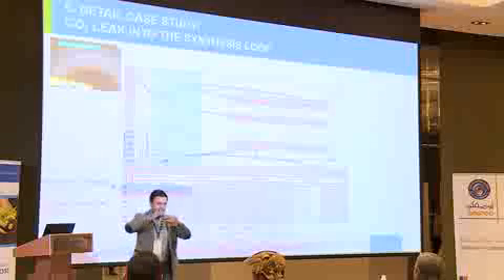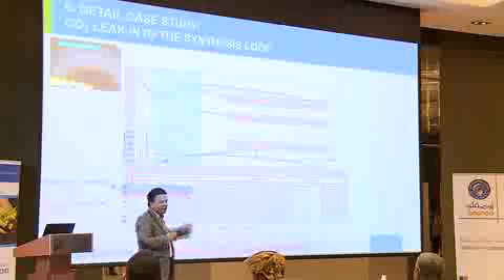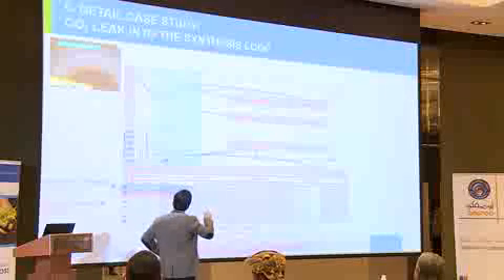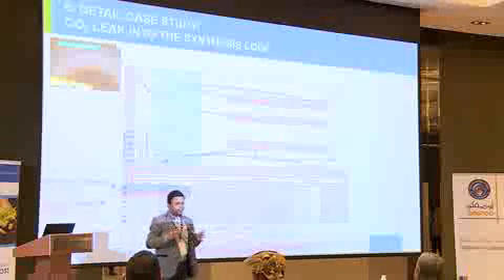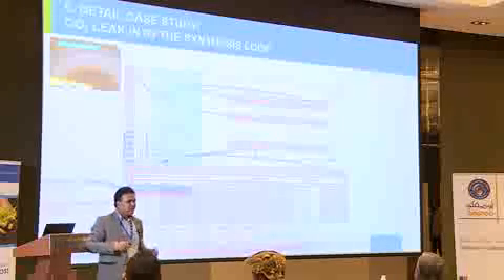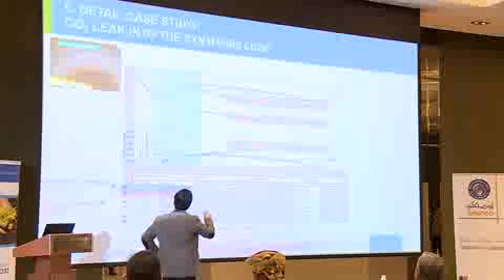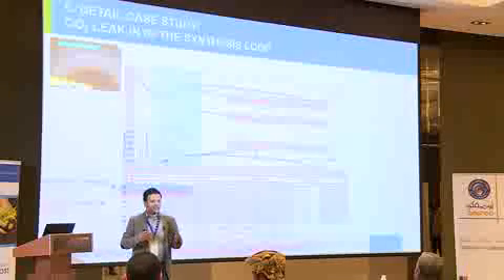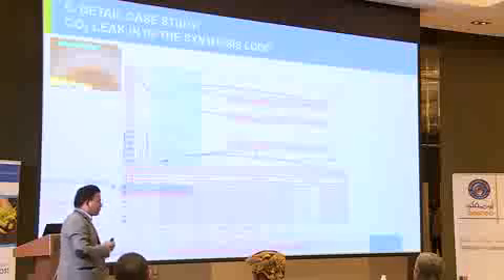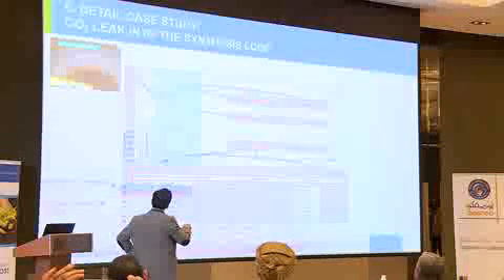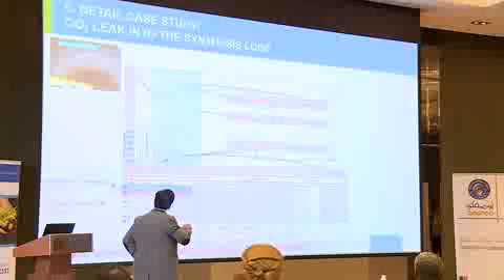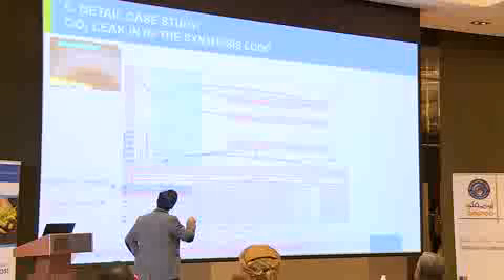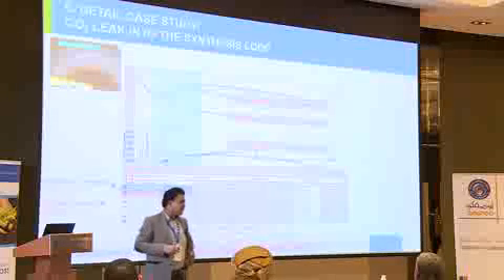This theory was further clarified when they looked at the top temperature of the stripper, the off-gas temperature of the stripper going to HPCC and ultimately to the reactor. They saw during that time there was a dip in the temperature. This is a fully traced line. So when there is no flow, it should have a fixed temperature. But during that period, the temperature was decreasing. So there must be something flowing through it. So the theory became stronger: the pressure of synthesis was lower compared to the compressor, and there was a dip in the temperature in the off gas of the stripper.